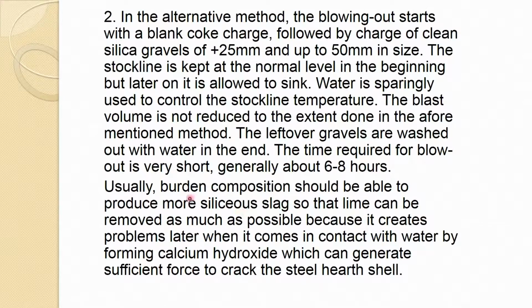and that expands, even such gases are also there, and due to expansion of that it exerts force. And when there is plenty of lime in that, that force could be of sufficient magnitude, and it can even crack the steel hearth shell, and sometimes even small explosions occur if that force is not taken care of in a proper way. So, it is a very essential step that as much as possible the lime should be removed by the end of the blowout period.